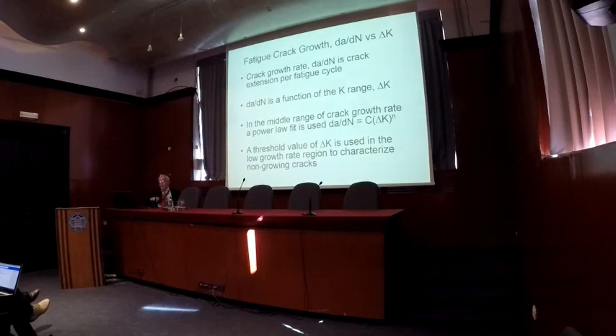So here's another one, fatigue crack growth, the da/dN versus delta K. And fatigue crack growth is a second behavior. The fatigue crack growth, da/dN, is crack extension per cycle, and it's a function of the K range, delta K. In the middle region of that, there's a power law that I'm going to tell you about in terms of Paris's contribution. And there's also a threshold. If you stay below a certain delta K level, you get non-growing cracks.